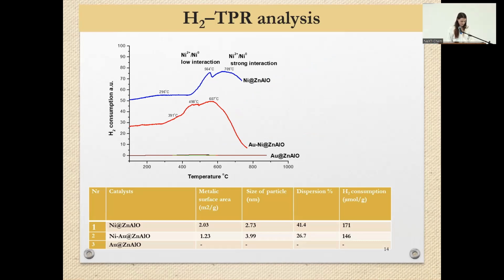The temperature programmed reduction measurements were carried out to analyze the reducibility of the nickel-supported catalysts, as well as the metal support interaction. Reduction profiles of nickel and nickel-gold catalysts were very similar. In fact, the thermograms can be seen as overlapped peaks with low interaction at low temperature and strong metal support interaction at high temperatures. The hydrogen consumption at low temperature can be assigned to the reduction of the hydroxy species on the surface. The introduction of gold has the effect of increasing the nickel reduction capacity. And here you can see the results from the hydrogen chemisorption presented in the table, which gives us the information that the active component dispersion decreases with the gold being added.